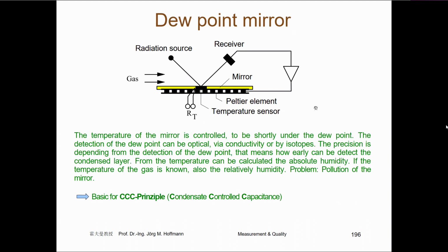It is also used. A problem, of course, is that you need a clean mirror every time. And when you have particles in the gas or other things, they cause the same change of light scattering as the water at this point, so that you need a very clean mirror every time, and that is in practical applications the most important problem. Therefore, the surface has to be cleaned and so on.